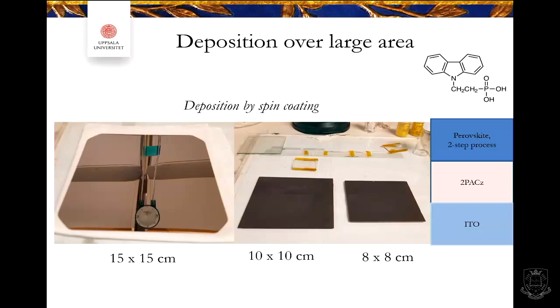And here, one of the first steps was to do a kind of half solar cell. So this is an inverted solar cell. As a hole transport material, we have this 2PACz molecule, which is this phosphonic acid with the carbazole group here. So that is used as the first layer, and then we try to see how good the wetting properties are. So what we tried here is spin coating. It is, of course, an enormous substrate to spin coat, and with the centripetal force we have a little bit different thicknesses over the surface, from the middle to the edges. But the variation in thickness is not that big, and it can be used, at least.